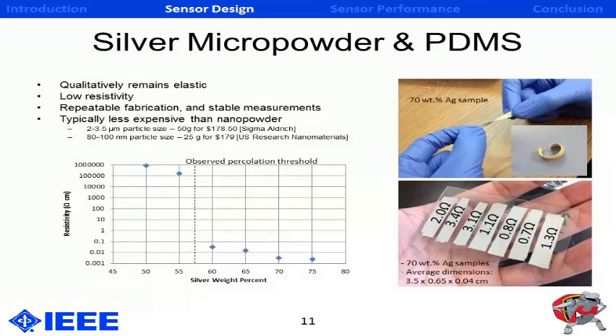Also, since the paper, there has been some characterization done of the silver micropowder and PDMS. Qualitatively, it remains elastic, which is simply demonstrated in these photos. It has a low resistivity. It's very repeatable in fabrication and produces stable measurements. It's typically also less expensive than nanopowder, which is what we used in the paper. In this case, we're using a 2 to 3.5 micron particle size, which is about half as expensive as the nanometer silver. On the bottom left, you can see resistivity as a function of silver weight percent, and we observed a percolation threshold between 55 and 60 weight percent. On the bottom right-hand side, you can see a series of samples from different batches demonstrating the repeatable nature.